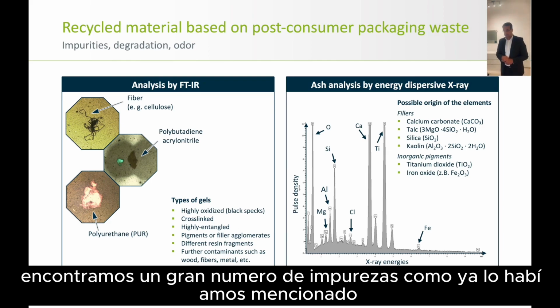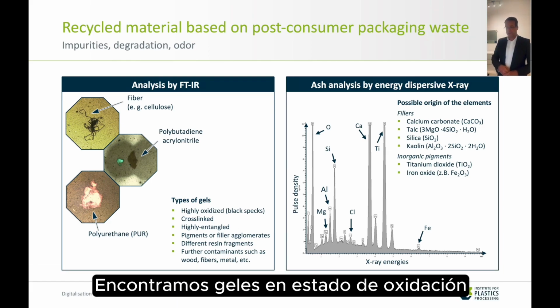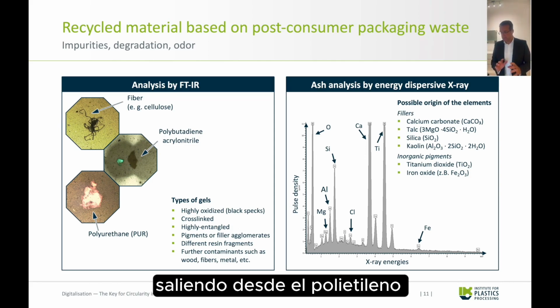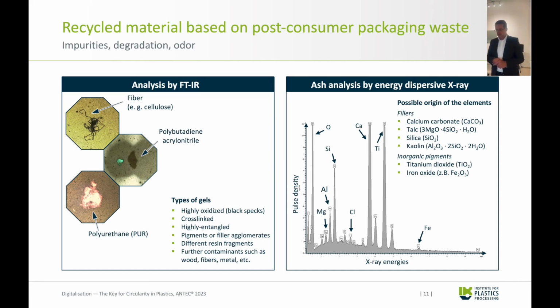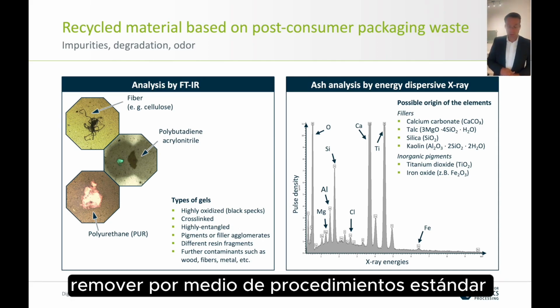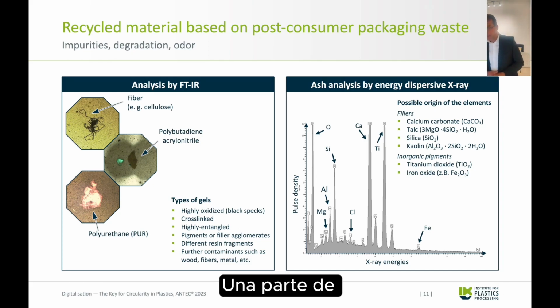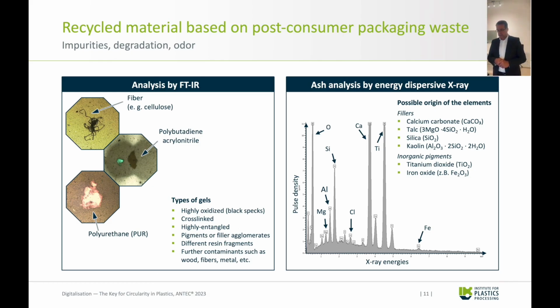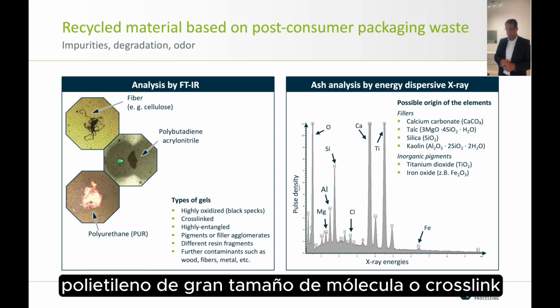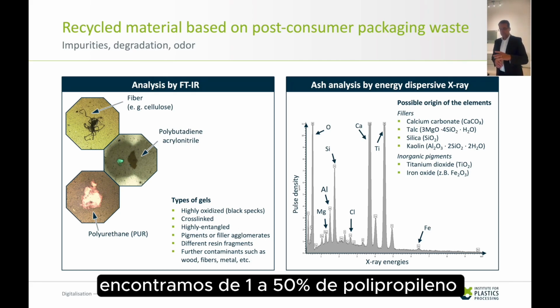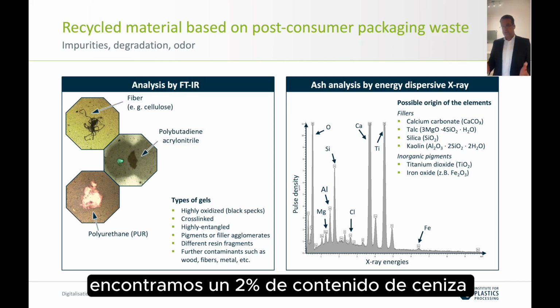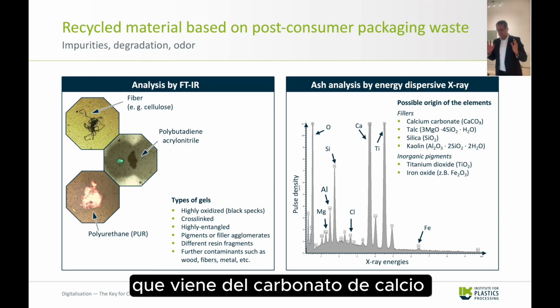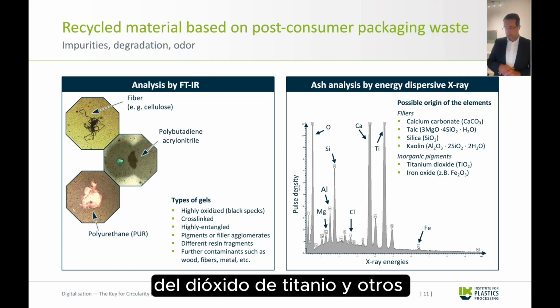We find a large number of impurities, as I already mentioned. We find gels, highly oxidized, in general coming from the polyethylene, which is hard to remove by standard processing routines. So we find a share of about 30% of high molecular or even cross-linked polyethylene. We find 1 to 15% of polypropylene. We find 2% of ash content coming from calcium carbonate, from talcum, from titanium dioxide, and so on.